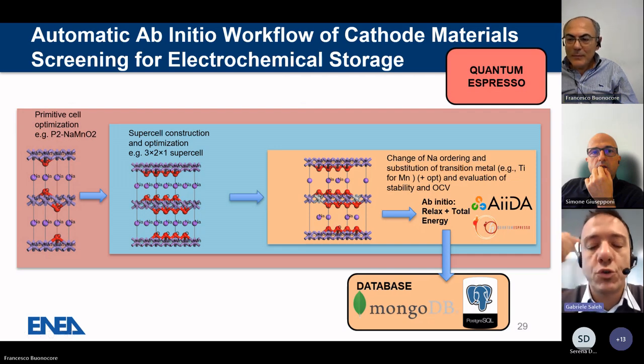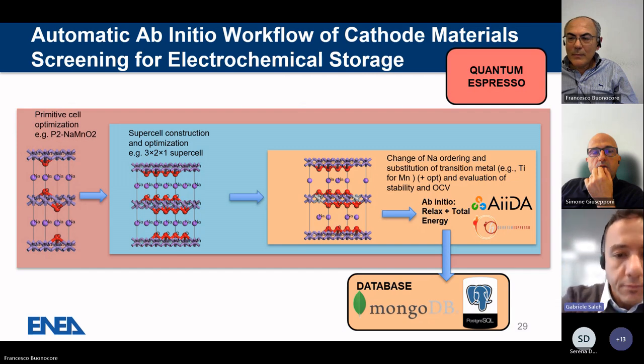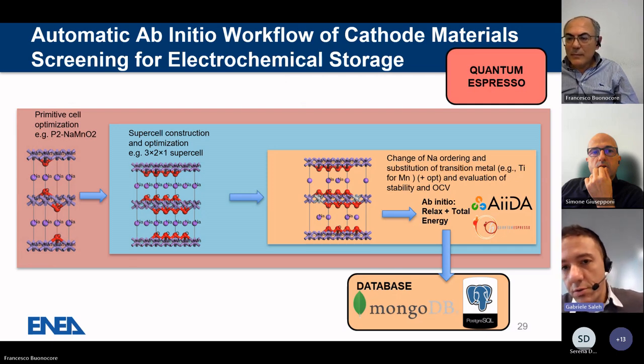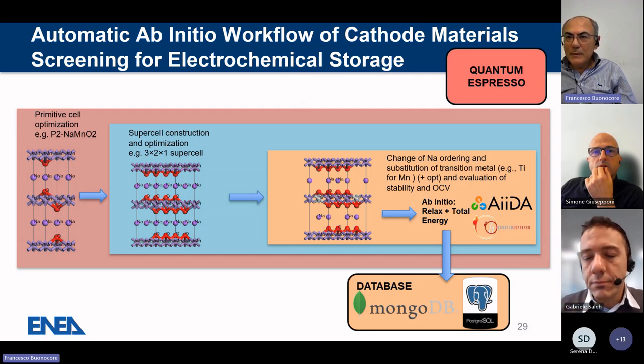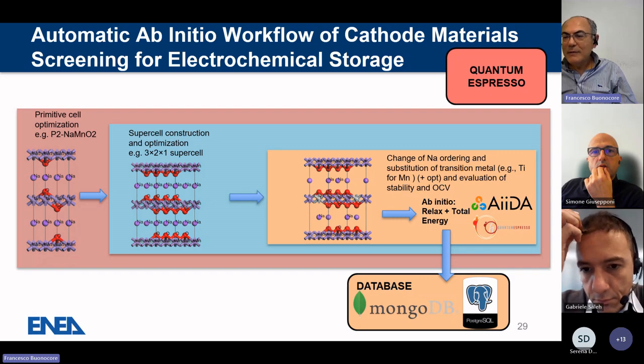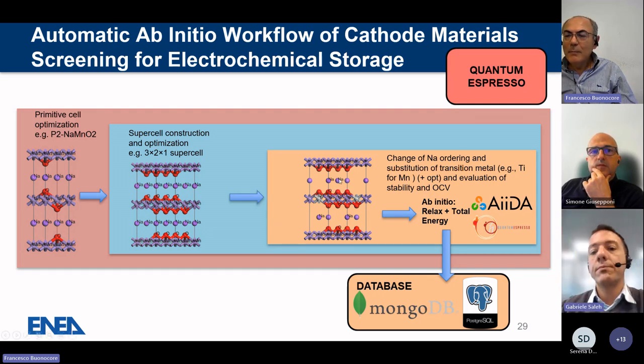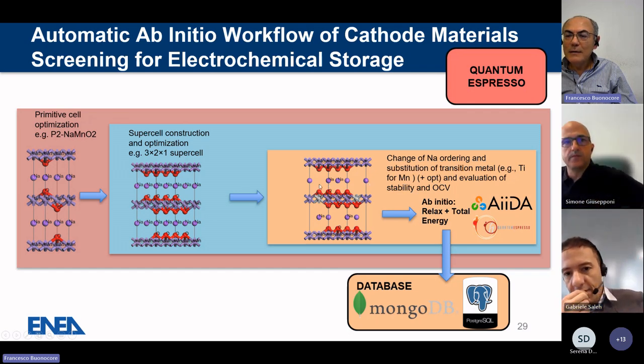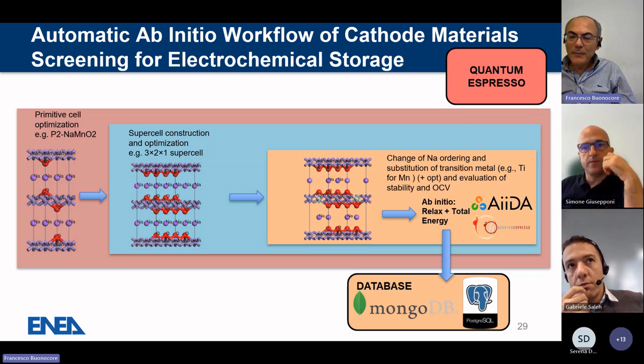Yes. And do you know how true is it? I mean, do you have some examples in which you substitute the transition metal and the structure stays the same or changes? Really, in the literature it is found that some of these crystals have the same structure, others have a different structure. Anyway, we are looking for the most stable system. So I suppose that it's stable enough to keep this structure. Probably the less stable systems do not keep the same structure. But we are looking for the most stable systems having this structure. Okay. That is the preferred one because it allows to intercalate and deintercalate sodium without distortion during the cycles of charge and discharge. Okay, clear.